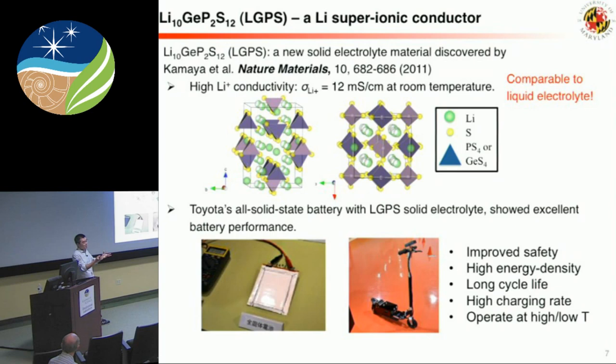That paper then tried to find all these materials with a BCC anion lattice and the lithium right at the tetrahedral site. But you still need some cation to hold it together. So that's one of the reasons, but our contribution is that if you have a BCC, it's great. But if you don't have a BCC, you can still probably insert a lithium into a high energy site to activate this mechanism and lower your barrier.